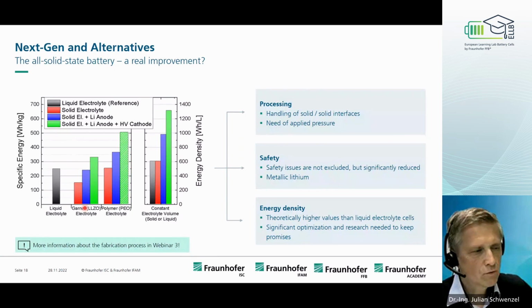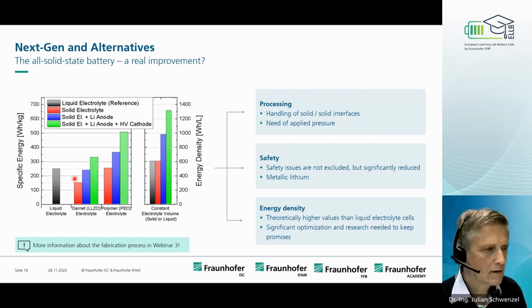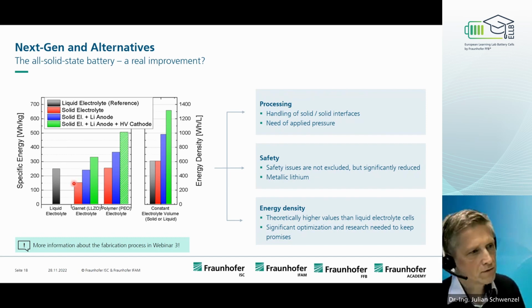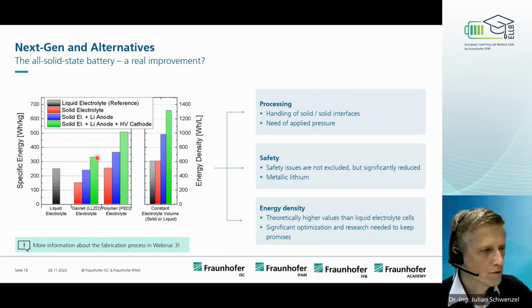But if you also use a high voltage cathode, you will clearly improve the energy density with this kind of material. So the key message to keep in mind is that if we exchange the liquid with a solid system, it becomes heavier, because the density of the oxide is higher than that of a liquid. This is why we have this reduction in energy. But by using other advantages, lithium metal or a high voltage cathode, you can improve it.